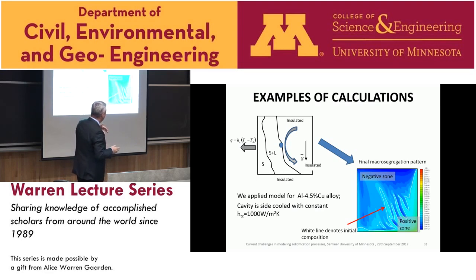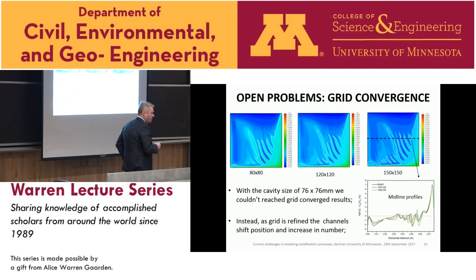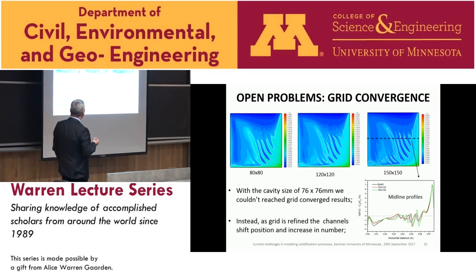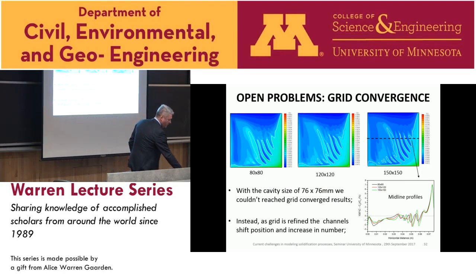Despite that, you have those significant channels. There are a lot of discussions about them: are they artificial or do they have a real physical meaning, and so on. This is related to the problem of grid convergence. We observed that it is very difficult to get grid convergence. We did the research with a cavity which is only 76 by 76 millimeters, and we imposed grids from 80 by 80 up to 150 by 150. And it was surprising that we couldn't reach grid convergence. It's very difficult, and very time consuming for calculations.